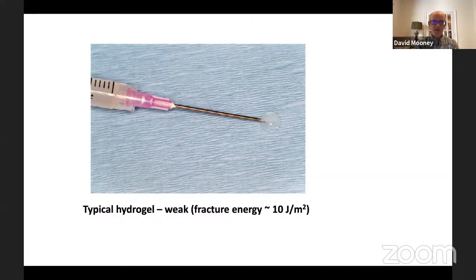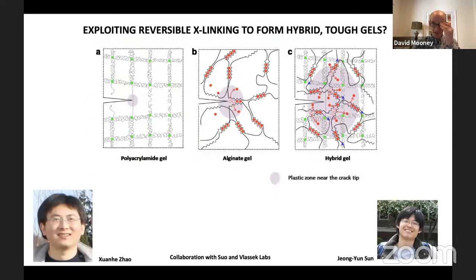was also in the lab, and he comes from a mechanics background. One of the observations that he made of these hydrogels we were using in lots of our studies is that they're basically very weak materials, with a fracture energy of about 10 joules per meter squared. And it's not surprising for this class of materials that they'd be very weak. As he was looking at Nate Huebsch and others doing these mechanotransduction studies and beginning to recognize the importance of the mechanics of the materials, he recognized that the ability of extracellular matrix to dissipate stresses could be an important principle, not just for cell interactions, but more broadly in terms of toughening materials.